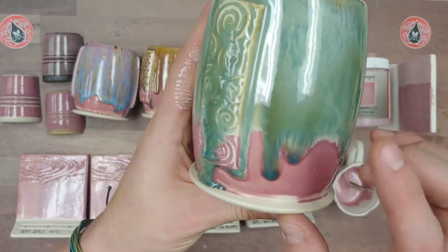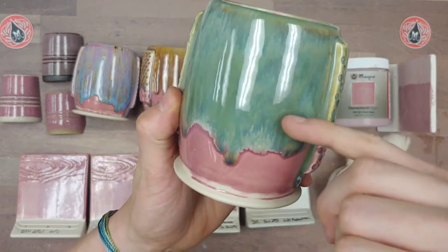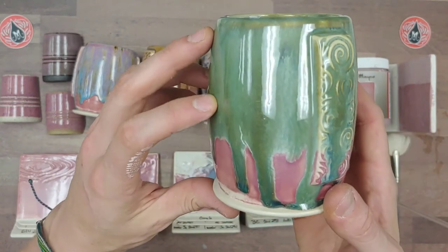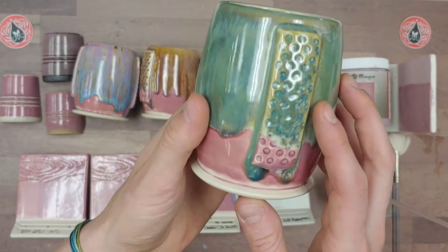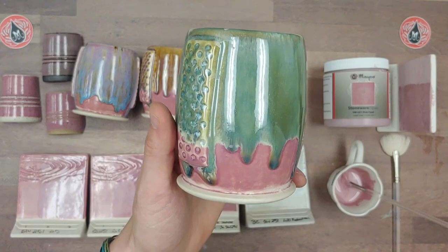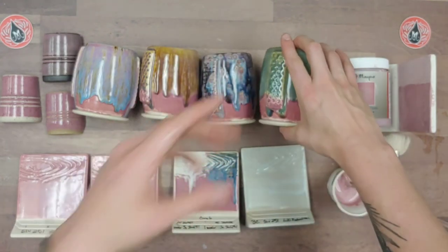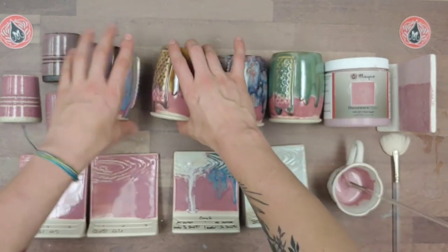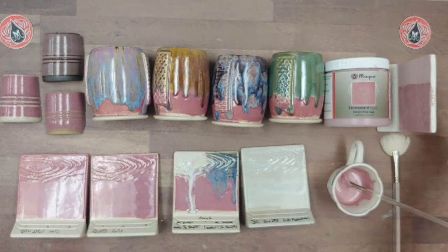Black Walnut over Pink Opal brings a green iridescence to the combination, which is not surprising for Black Walnut, and there is some mobility. If paired with a matte or standard gloss glaze, there probably wouldn't be much movement at all. How mobile a glaze ends up being really depends on how heavy you apply it and what glaze you're pairing it with.